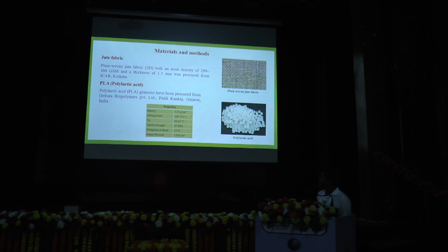And the materials: jute fiber, the plain jute fiber 2D fabric, a plain woven fabric with an areal density of 290 to 300 GSM and a thickness of 1.3 mm, procured from ICAR Kolkata. And polylactic acid granules have been procured from Dekla Biopolymer Private Limited, Gujarat, India, having a density of 1.25 gram per cubic centimeter.